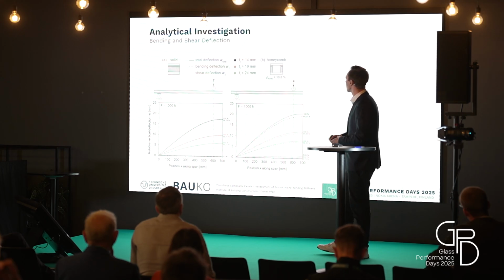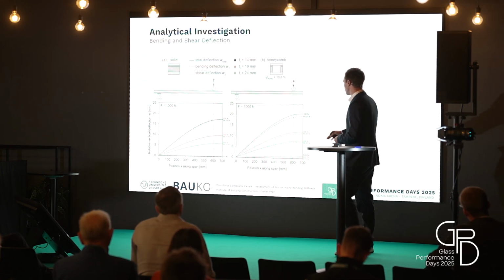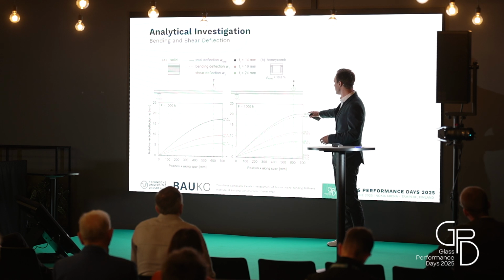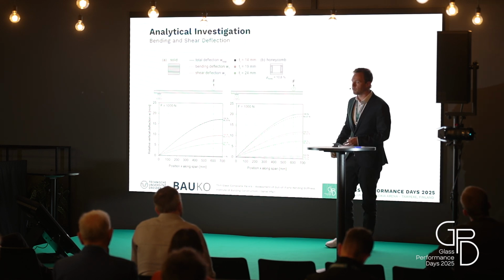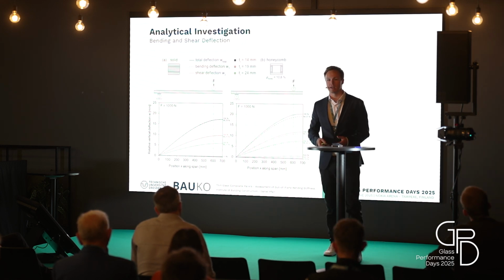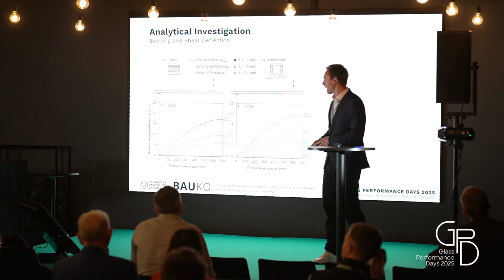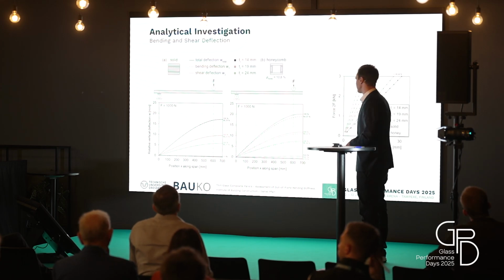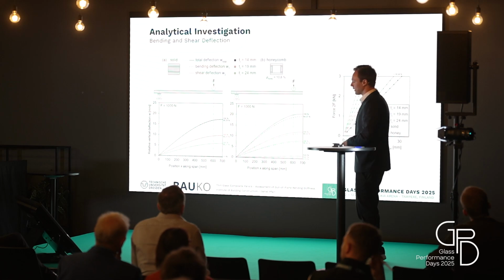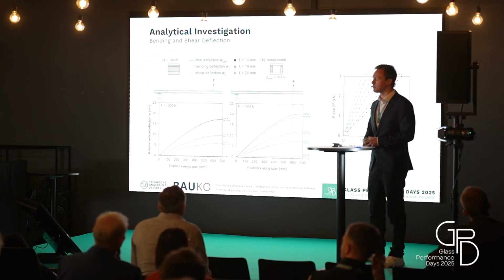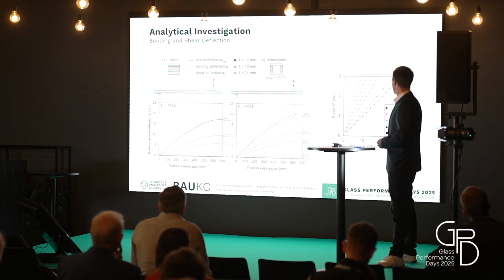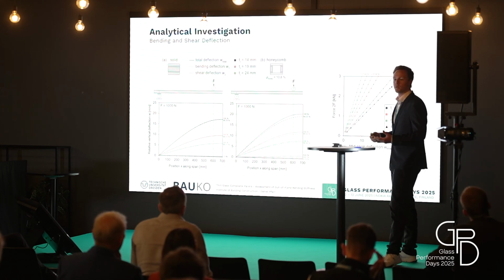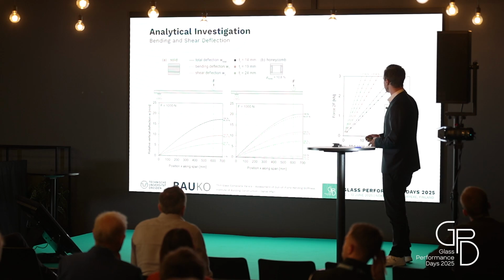And on the right-hand side with the honeycomb assumption, we can already see that we increase the shear deflection, we increase the total deflection, and therefore we have to take into account the shear deflection of the composite panel, and that is only for this one example. By calculating the deflection of these panels, we get the diagram with the total mid-span deflection on the right-hand side, and on the left-hand side the force we are applying in our 4-point bending test. This graph we will later compare with our experimental results as well.